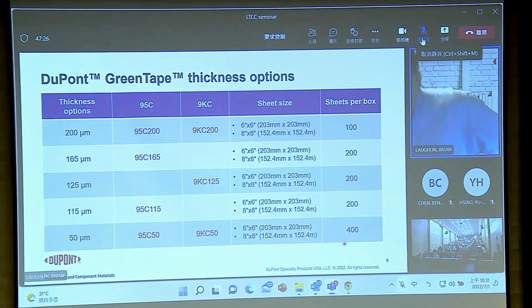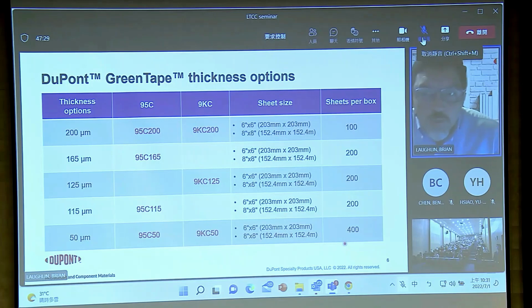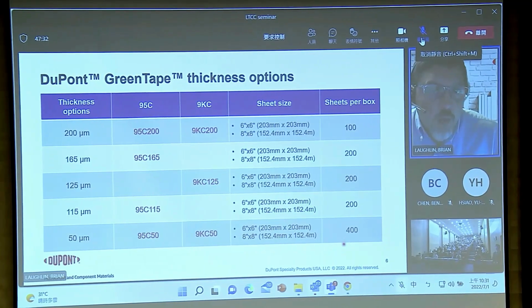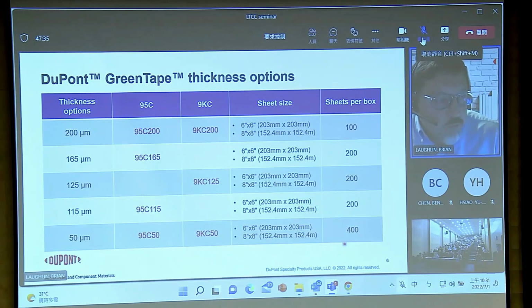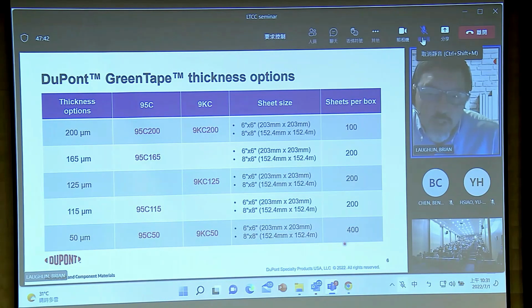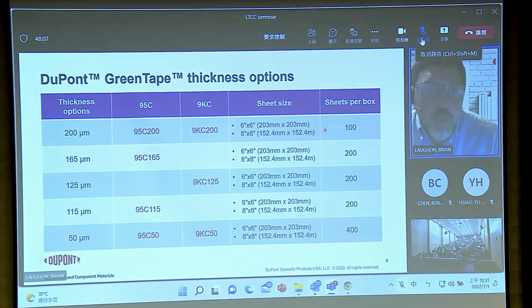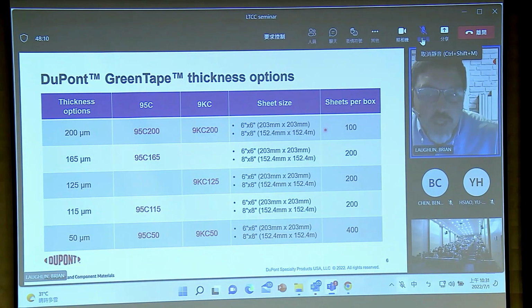So the materials that we sell today, if you were to talk to someone about procuring a material, we have two main product lines that we'd like to present today. One is 95C, a lead-containing system, and 9KC, which is a lead-free system. And we'll sell it by increments of green tape thickness, indicated by 200 microns, 165 microns, 125 microns, 115 microns, etc., in select sheet sizes, usually 6 inch by 6 inch or 8 inch by 8 inch. And we sell it in a box, with 100 to 400 sheets per box. And so those are the product variants that we have set up today.